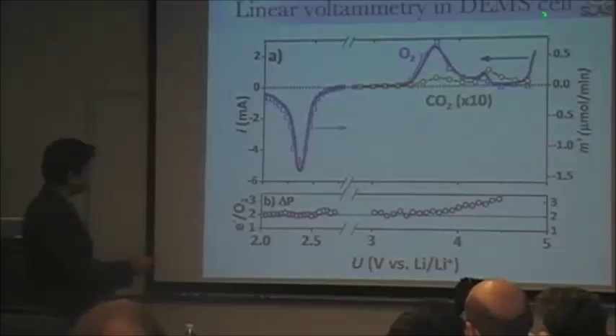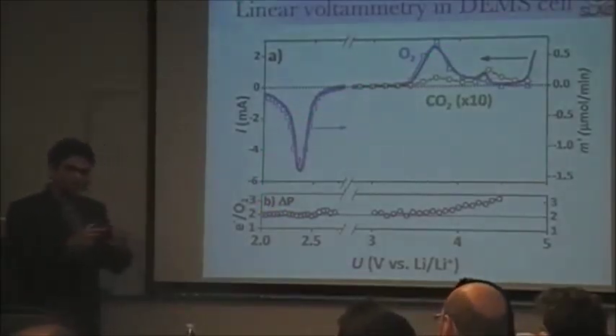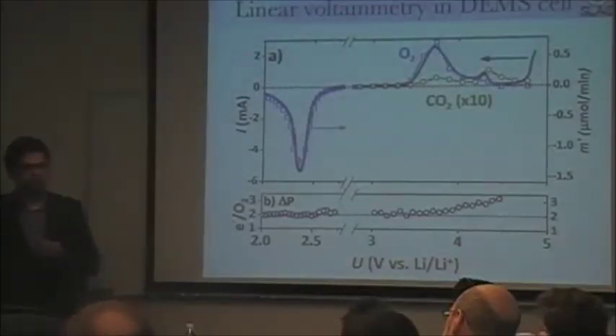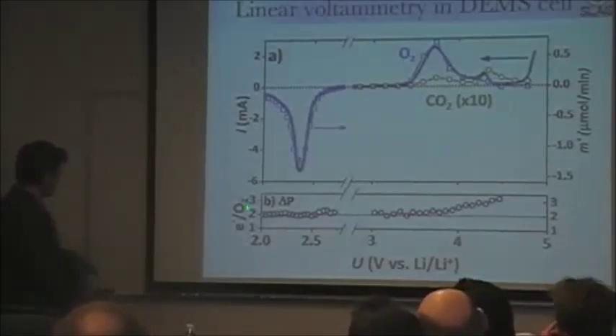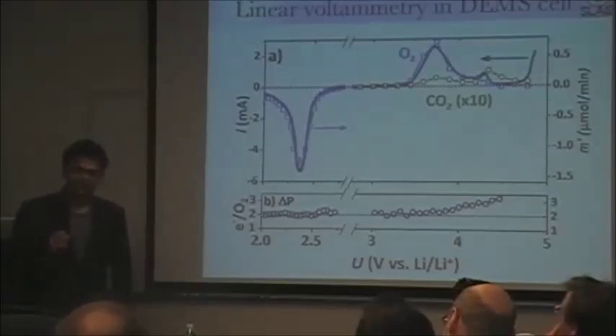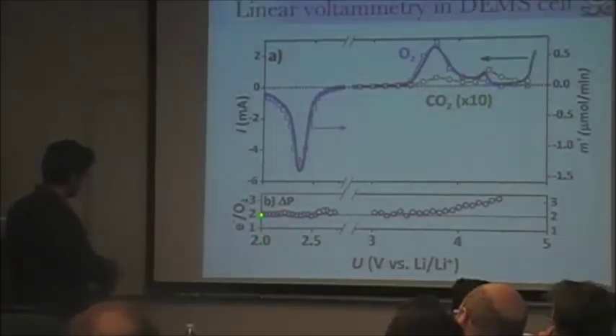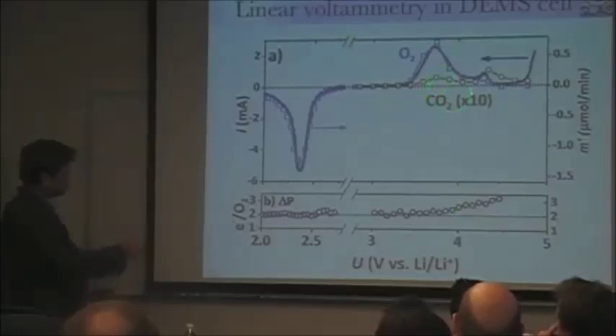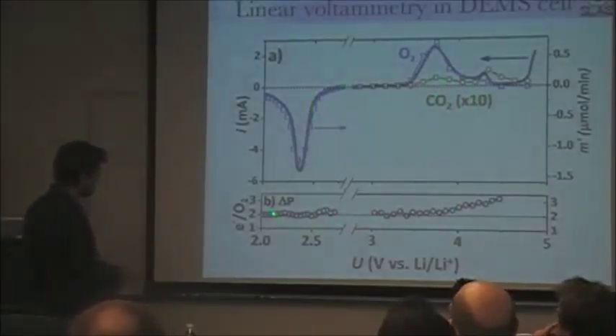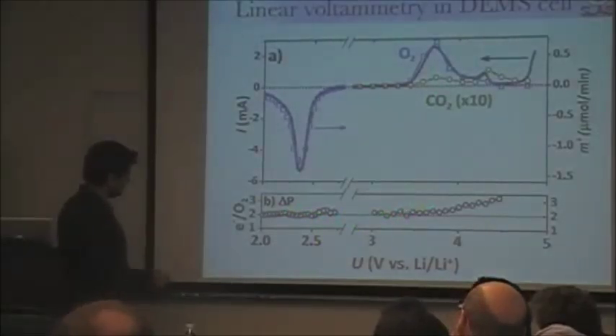This is done in a DEMS cell at IBM, where a battery is hooked up to a mass spectrometer to calibrate gas products consumed and evolved. The key parameter you can extract is electrons per oxygen. Under discharge, the reaction is nearly perfect at 2 electrons per oxygen. Under charge, it's almost perfect at 2 electrons per oxygen initially, but then starts to deviate, with some CO₂ appearing. This reasonably proves that the reaction under discharge and charge is the reduction of oxygen and then evolution of oxygen.